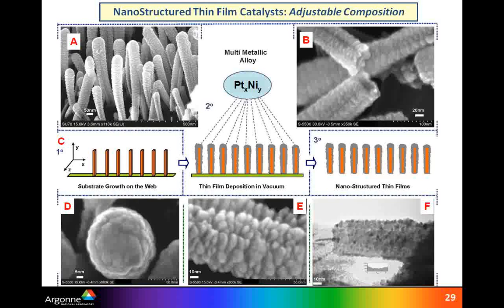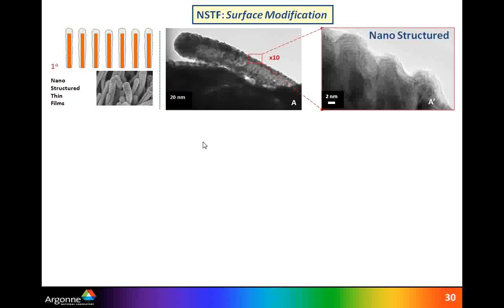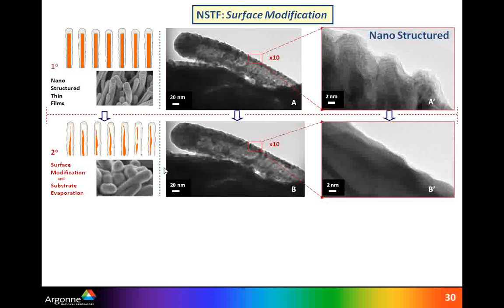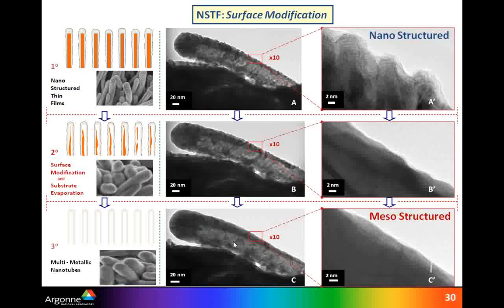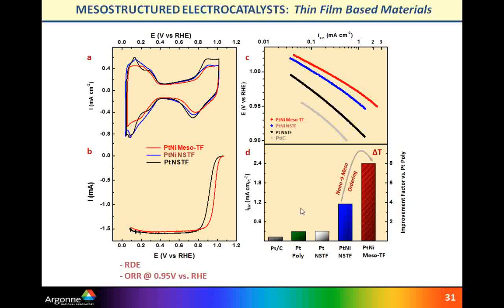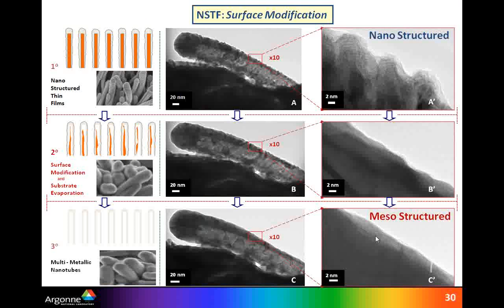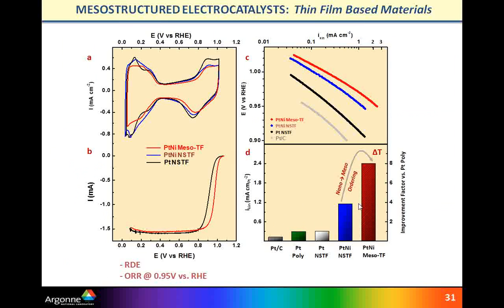In this particular case, we were working with a NSTF type of catalyst, and one can see the initial surface morphology is highly corrugated, with nicely pronounced features on the surface and a highly grained structure. So we applied our annealing protocol, and we were following with in situ TEM in order to see how the surface and near-surface morphology would change. That would be the initial stage, and after several minutes we could see the surface was getting smoother, and finally we ended up with a surface which was clearly rich in crystalline facets and almost completely flat. What was intriguing again was to check electrochemical properties, and regardless of a slight loss in specific surface area, because we were going from highly corrugated to more smooth, we were able to observe a substantial increase in specific activity.